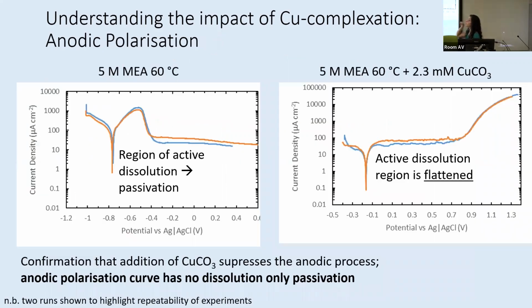As we start to look at things like anodic polarization, and I know not everyone will be familiar with these particular techniques, what you can see is that when there's no copper, which is on the graph on your left, and when there is the addition of 2.3 millimolar of copper carbonate on the right, the graphs are different. And so you'll have to trust me in believing that this shift indicates that we no longer have active dissolution of our metal. And you can see that that's been flattened out, which means we've got passivation. So this is one of the indicators that that's what we have going on.